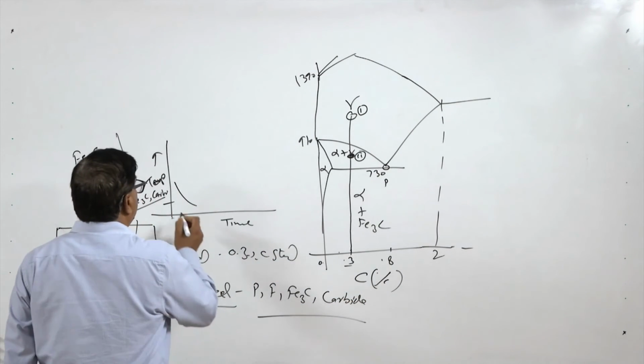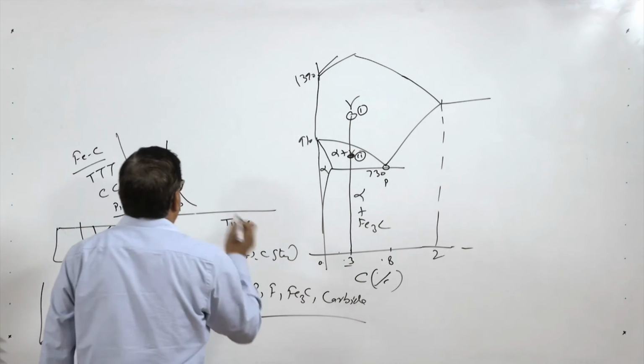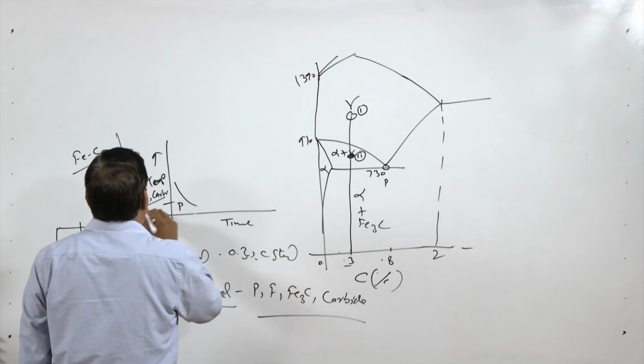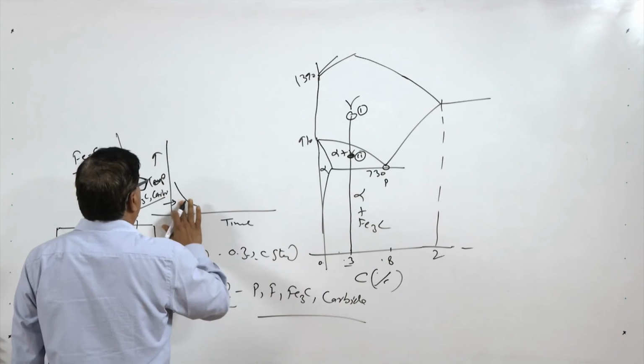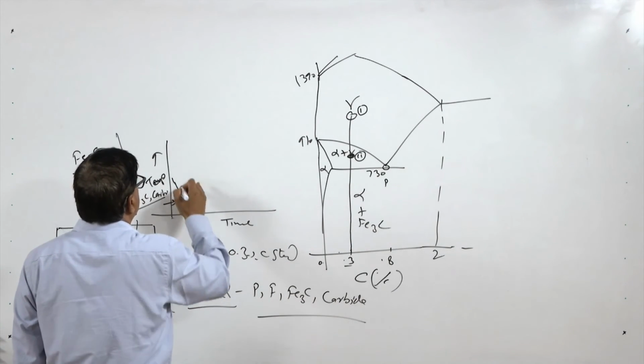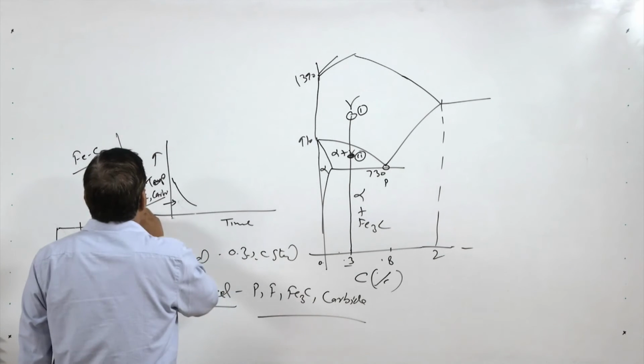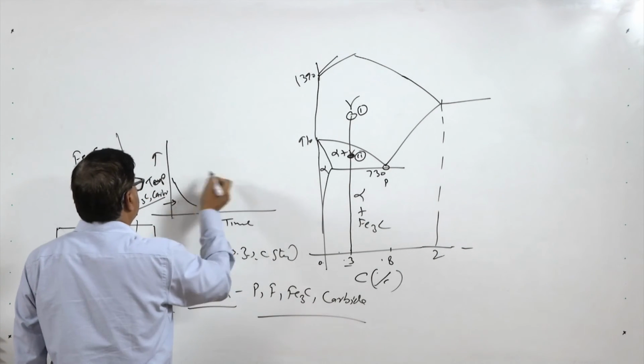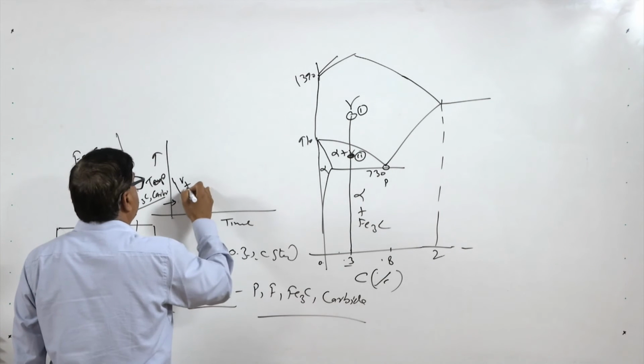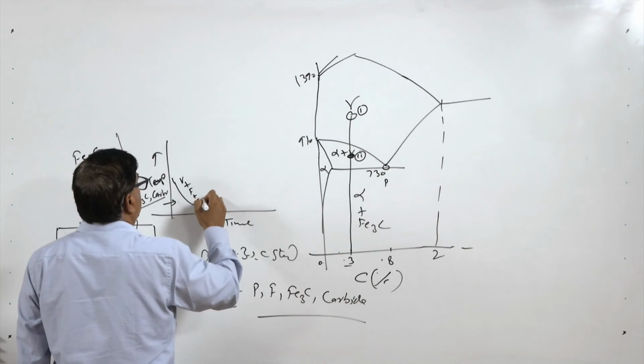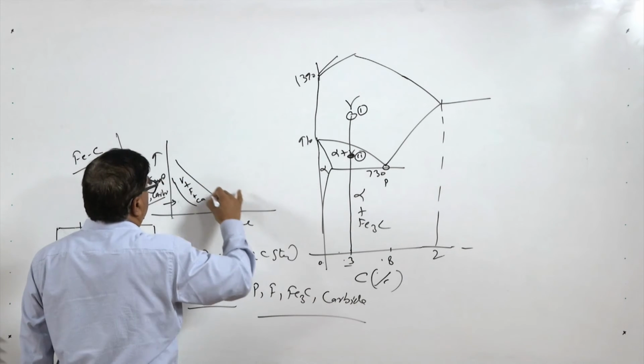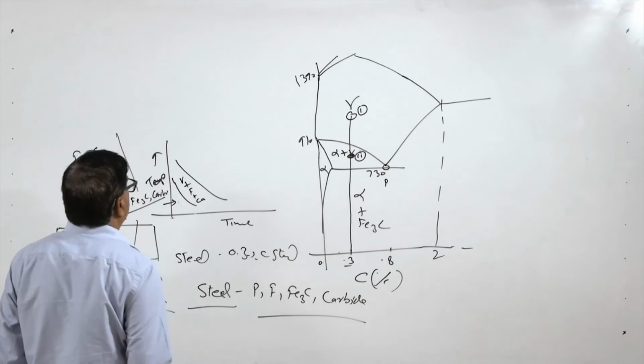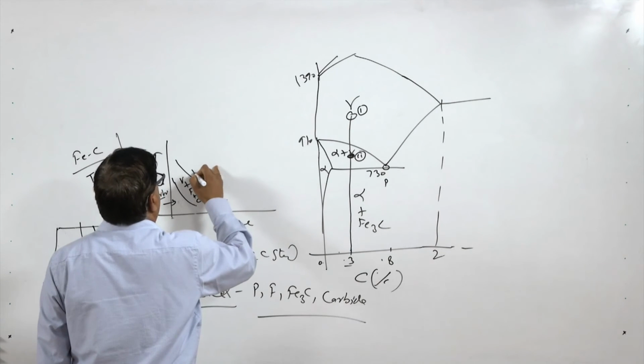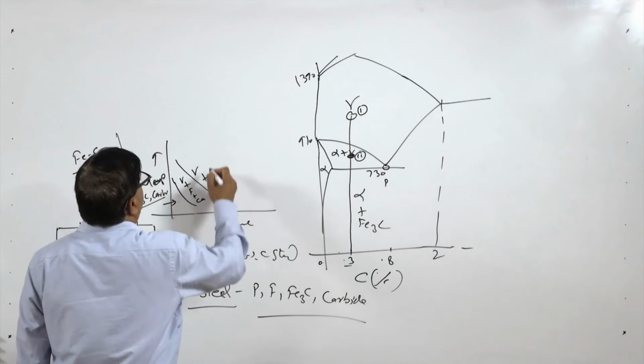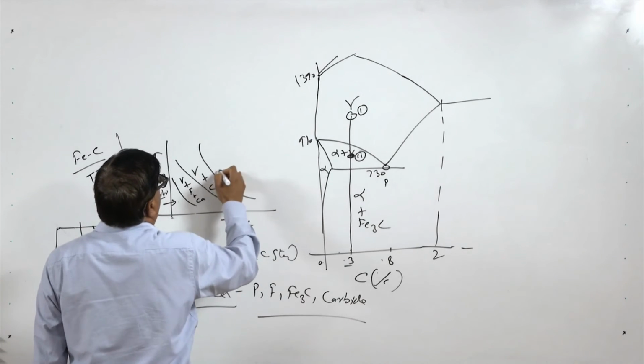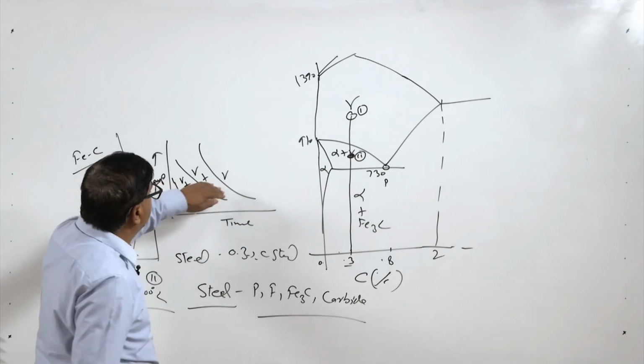So, first of all pearlite transforms into the austenite. Here we have pearlite in all these phases in this area, and as the heating continues at a high temperature, our pearlite transforms into the austenite. So, we get austenite plus ferrite plus carbides. If heating continues at high temperature for long, then ferrite transforms into the austenite. So, we have austenite plus carbides. If further heating continues for long, then we will have only the austenite, but this is inhomogeneous.